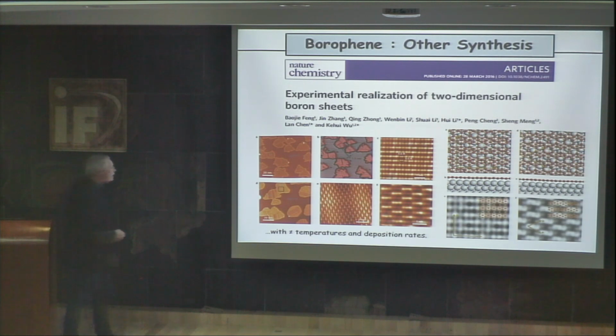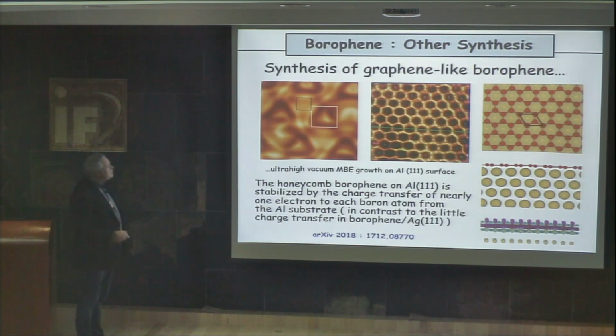A few months later, a group of Chinese researchers also showed that it was possible to synthesize, with different temperatures and different deposition rates, other types of boron structure. And very recently they were even able to make the analogue of graphene in the case of boron. So a perfect hexagonal structure, but composed only of boron atoms in this case.